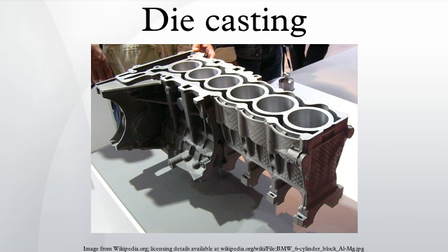The idea was to use a second piston to apply pressure after the shot had partially solidified around the perimeter of the casting cavity and shot sleeve. While the system was not very effective, it did lead the manufacturer of the Acurad machines, Ube Industries, to discover that it was just as effective to apply sufficient pressure at the right time later in the cycle with the primary piston. This is indirect squeeze casting.